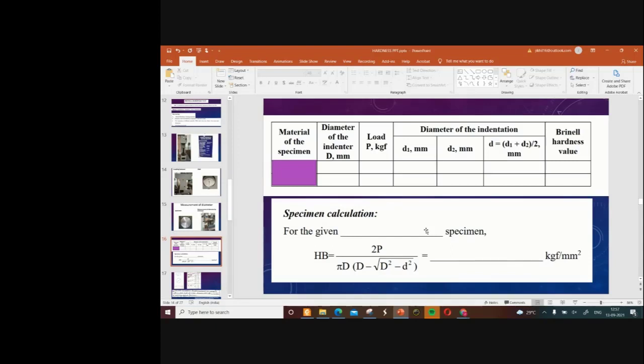So this will be the table of observations: material specimen, diameter of the indenter, then the load applied, diameter D1, D2, and then the average of the diameter and the Brinell hardness value. So the calculation is HB. Brinell hardness is given by 2P divided by pi D into D minus root of D square minus small d square. In this, P is the total load applied on the specimen, and D is the diameter of the indenter.